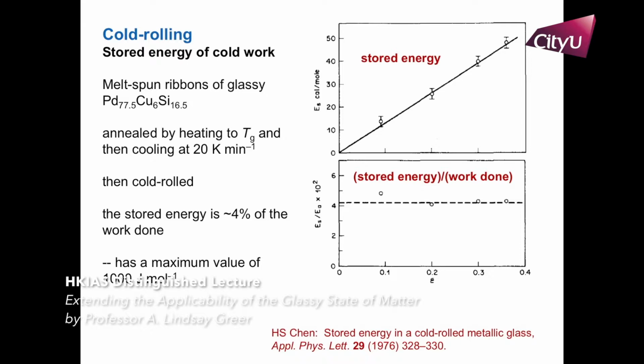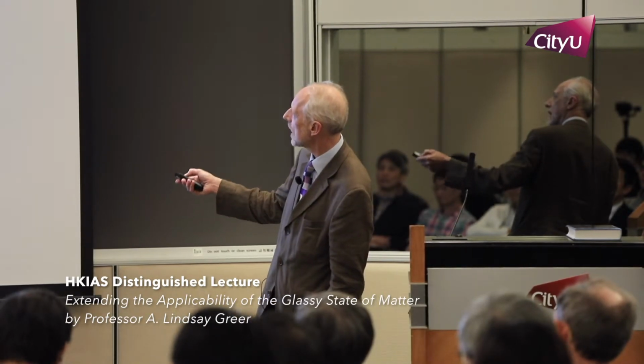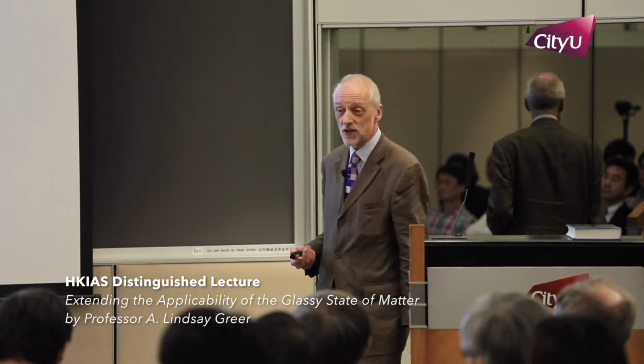And one of the things you could do is cold rolling, and then you store energy in the system. And you can work out how much energy you store in relation to how much mechanical work you have performed on the material. This is a classic topic for crystalline metals. Behavior for the metallic glass is nice and linear. You store a few % of the work done. Interestingly, that's roughly the same figure as you would get for a crystalline metal. For the crystalline metal, this is achieved by generation of dislocations in the structure, which are defects. They have a higher energy.